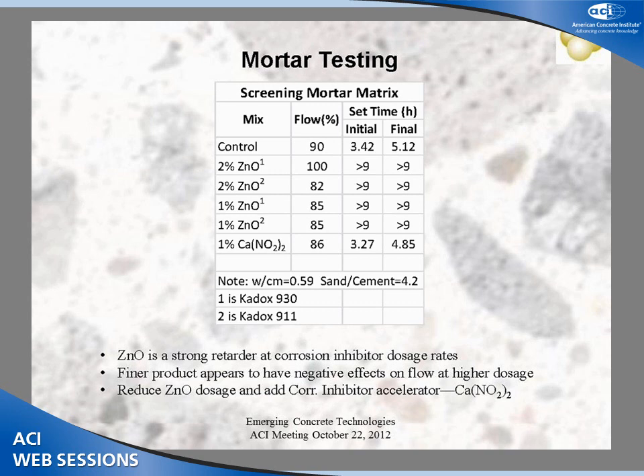You can see that the mortar mixtures that had the footnote 1 were with the Kadox 930, the coarser product of the two. And this one and this one right here use the Kadox 911, the finer product. But basically, the introduction of 2% zinc oxide of the 930 coarser product did increase the flow capabilities of the mortar mixture.